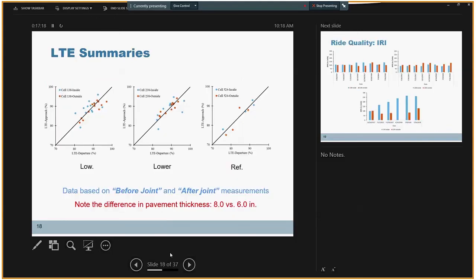Here in this slide, I have a summary of the LTE values we obtained for the three concrete types. Starting from left: concrete prepared with low cementitious material 500, concrete prepared with lower cementitious material 470, and the reference concrete, 570 pounds per cubic yard of cementitious material. The blue marker points here present the data obtained from the inside lane, which was exposed to traffic, and the red dots present the data from the outside lanes, just exposed to environmental loading, no traffic load.